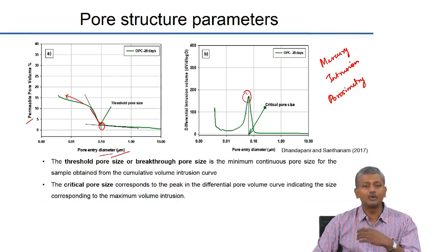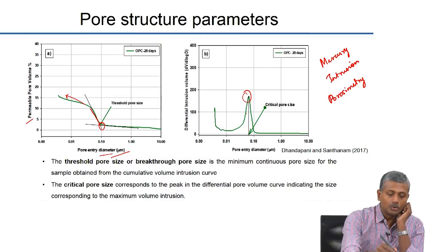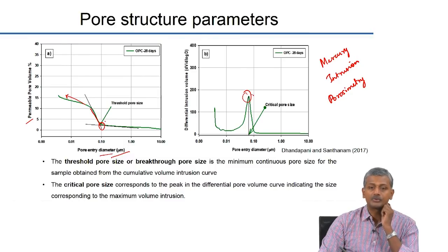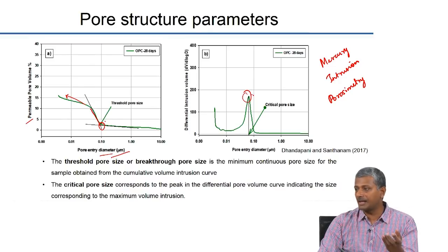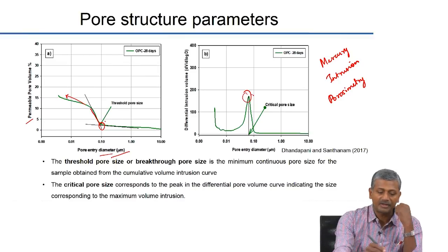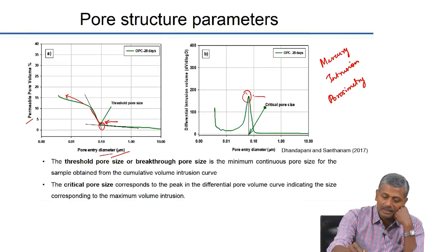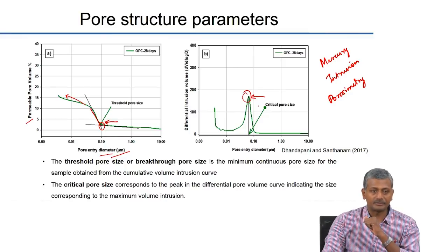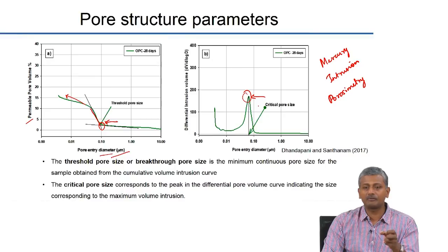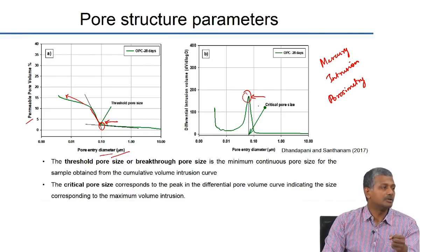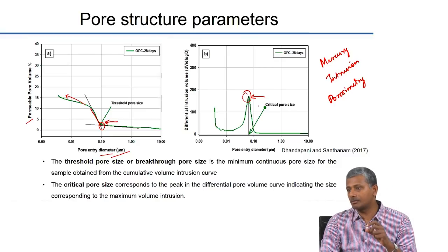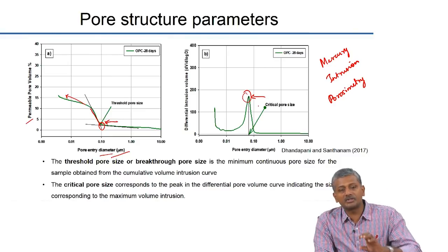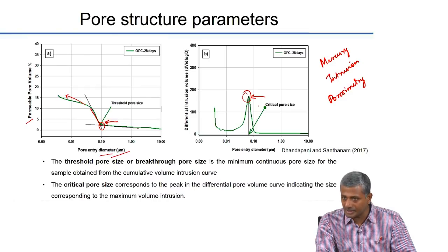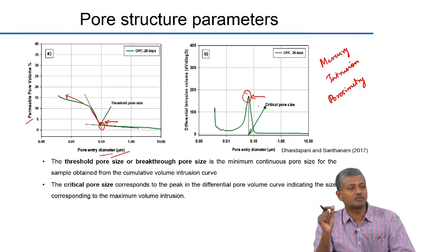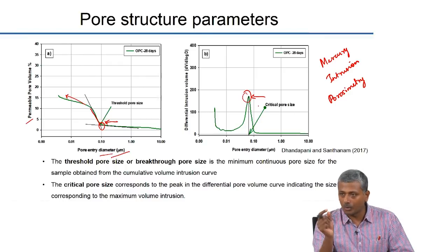So, when you reduce your water to cement ratio in the system, both the threshold pore size and the critical pore size will tend to reduce. When you substitute cement with silica fume or slag or other mineral additives, you can again expect the same effects, that the threshold pore size decreases and the critical pore size also moves to the left. So, MIP is a very useful experiment from that regard, that it can actually help you determine the pore structure parameters that are existing inside your concrete. Only problem here is you are not going to be able to measure this for the ITZ, because for the experiment you will have to take very small samples from your concrete, and these samples will be essentially the mortar within the concrete.